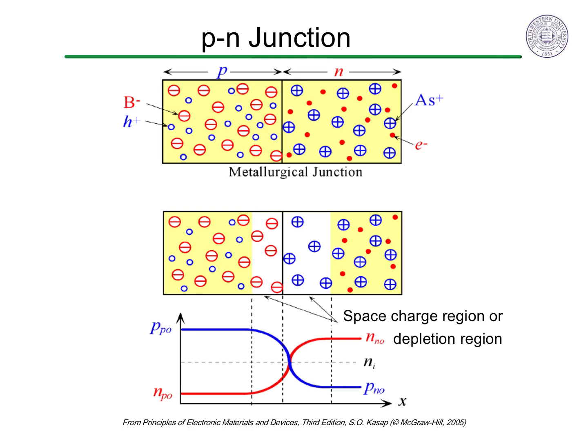The interface of the p-type region becomes negatively charged due to the boron negatively charged ions with no holes to compensate. And the n-type region becomes slightly positively charged due to the uncompensated arsenic positively charged ions. We call this interface the space charge region because of the uncompensated charges. It is also called a depletion region because the charge-carrying electrons and holes are depleted.